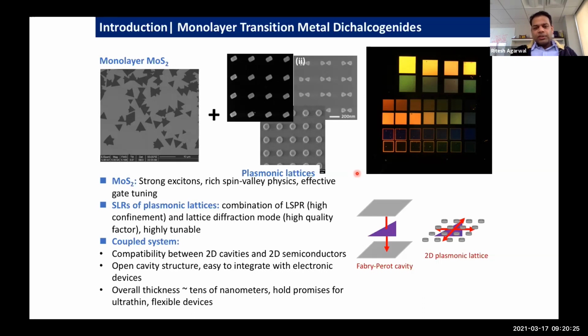So instead of putting a single nanoparticle and confining light at that length scale, we wanted to do something on a larger scale. Through trial and error, and because of the vast literature available on these lattices of plasmonic particles, we were able to create these crystals of plasmons. At an individual particle you have localized plasmons, and collectively over a large scale of this lattice, one can have a lattice mode, which is nothing but the in-plane diffraction mode of these plasmons. By doing this, one can engineer the optical modes of this plasmonic lattice, and it couples very nicely to the underlying two-dimensional system.